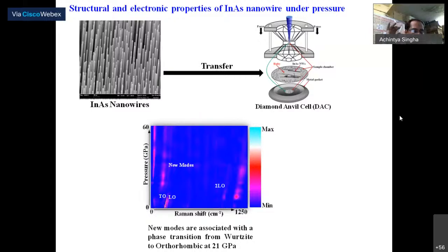Now, this structural property we know will change, but I want to show you in this work how, using Raman spectroscopy, we can get the change of electronic band structure within the system. As we apply pressure, the band gap will increase. If you do Raman spectroscopy with a fixed laser line and apply pressure, the pressure tunes the band gap, and as the laser line is fixed, sometimes the band gap of the system is close to the laser frequency. There you can see resonant Raman behavior, so you will see some intensity enhancement.